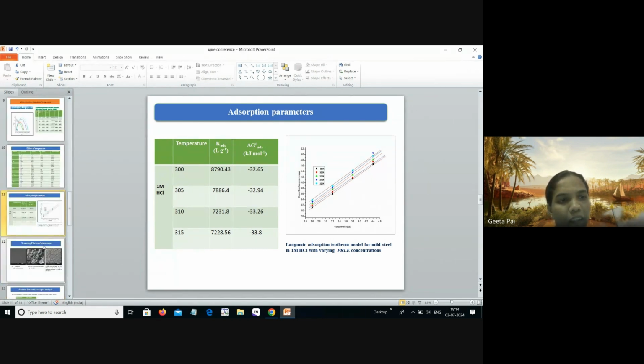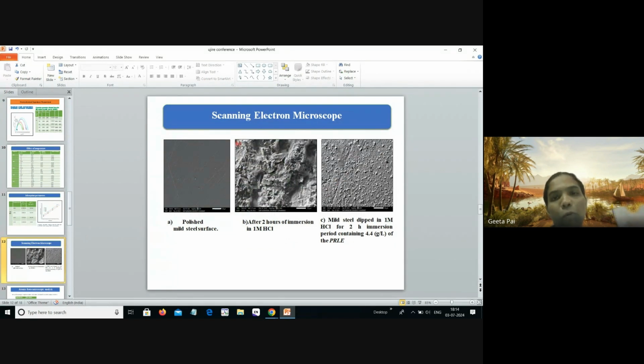Further, the morphological variation of the MS surface can be confirmed by the scanning electron microscope as well as AFM and contact angle technique. Here, figure A is the highly polished metal surface. It does not contain any defects, it means that the metal surface is highly homogeneous.